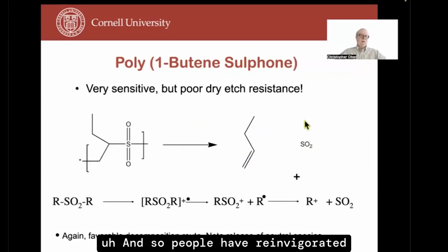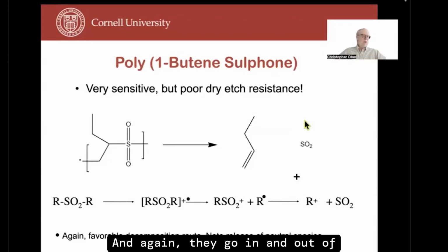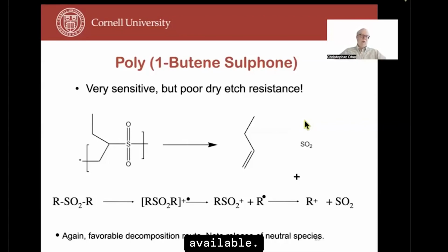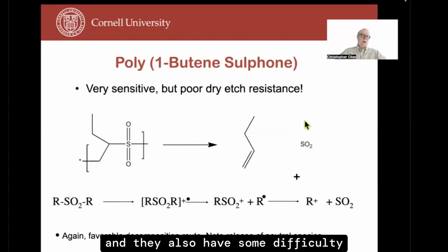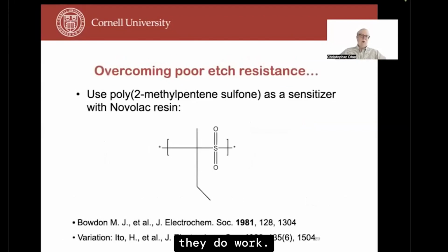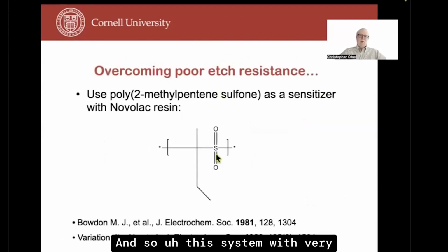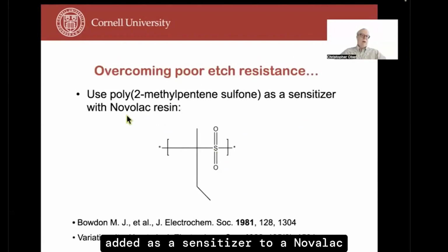And so people have reinvigorated these materials for extreme ultraviolet lithography with some success. These types of polymers were, as far as I know, first looked at Bell Labs as a mask writing resists. And again, they go in and out of fashion depending on what's available. They're somewhat difficult to make, and they also have some difficulty in handling. So there are other systems that are more popular, but they exist and they do work. And so this system with very poor etch resistance can be added as a sensitizer to a Novolac resist system, as it was done at Bell Labs, and then it makes a better patterning system.